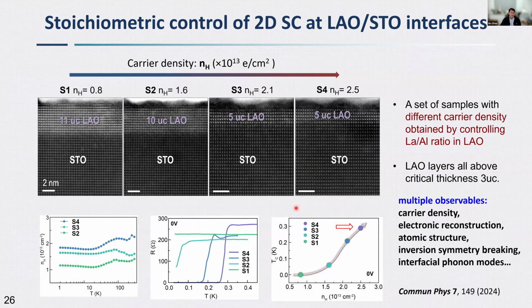So we are basically applying the same method to look at our system, but in this case we try to understand how the two-dimensional electron gas affects the local vibrational modes and correlates with the superconductivity. So we have, as I said, 4 samples. In this case, because we can't do electrostatic gating inside the electron microscope, we use the LAO layer to control the charge doping, specifically by the lanthanum aluminum ratio. You can change the charge doping from 0.8 all the way to 2.5 times 10 to the power of 13 electrons per square centimeter. And this will tune the sample from non-superconducting all the way to almost optimal doping level with a TC of about 300 millikelvin.